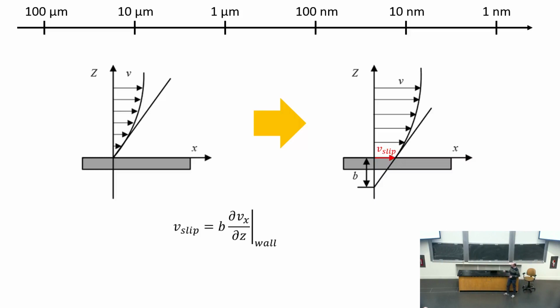A way to consider this is that you need a different boundary condition. This one was proposed by Navier himself: you define the slip velocity as the gradient of the velocity profile at the wall times b, the so-called slip length, which is the length beyond the wall at which the extrapolated velocity profile goes to zero. You can also think about this in terms of an equilibrium between different stresses. Here the force at the boundary is the area times the viscous stress.